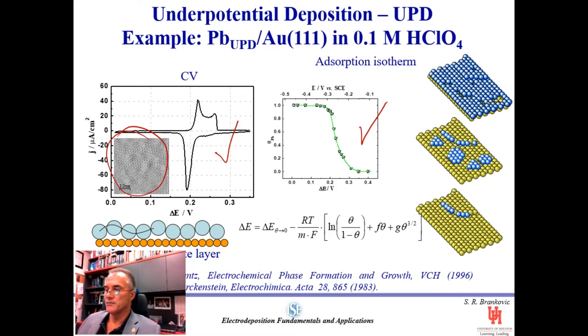And you can see that by choice of the underpotential, we can deposit a very finely controlled amount of lead, whether it's just decoration of the defects, whether we want to nucleate and deposit more on the terraces, or we can put the full monolayer. It's just a matter of what kind of underpotential we choose. The relation between the coverage and the underpotential is well understood. It can be described by certain adsorption isotherm models. One I'm showing here with the green line in the graph is defined by the Bockris-Swinkels isotherm, and it's basically Langmuir based, which has Frumkin and Temkin additive parts which describe the interactions in the layer.